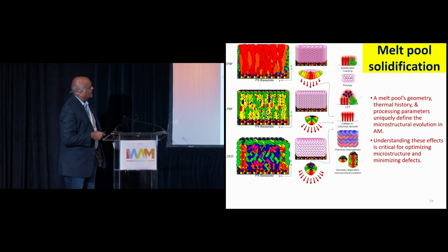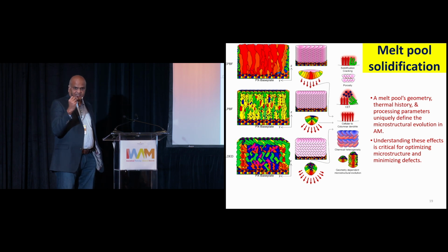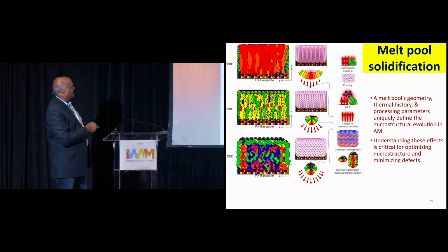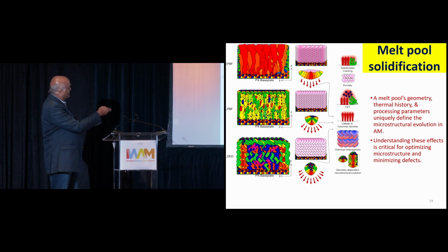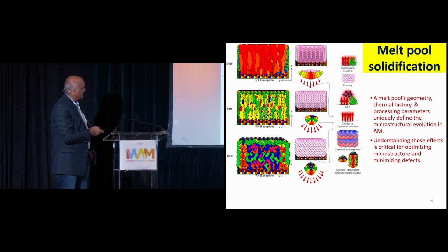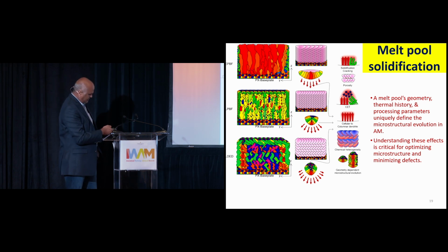So the melt pool, at any given instance, determines the solidification characteristics, which determine the kind of microstructure you get, as illustrated by these examples. Whether it's a shallow one, as in electron beam powder bed fusion, versus LPBF where it's not so shallow, versus DED which is a much larger scale—it changes the microstructural characteristics. We just wrote a nice review on this very topic.